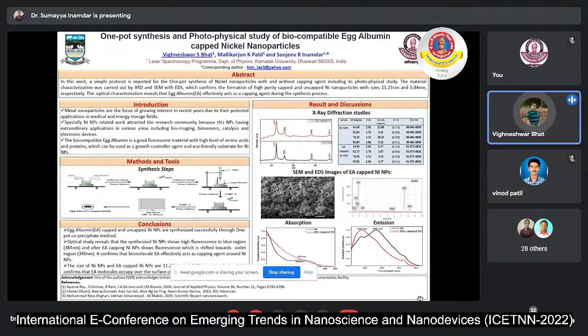Initially, after adding the reagent and salts, I stirred the solution for 20 minutes, then added sodium hydroxide to it. Then the color slowly changed from greenish to bluish. Then I took the egg albumin as a capping agent, heated it up to 80 degrees Celsius, and added it dropwise to the initially prepared mixture. After 20 minutes of stirring, I added sodium borohydride to it.